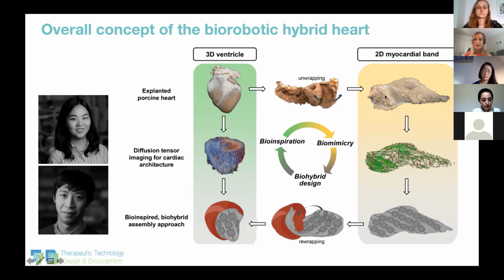And then we collaborated with Professor Chris Nguyen at MGH, or Mass General Hospital. He's also part of the Martinos Imaging Center, and he does advanced cardiac magnetic resonance imaging. In particular, we use diffusion tensor imaging, which you see here. You can basically use a technique called tractography to outline the orientation of the muscle fibers in the band. So now we have this 2D band and we scan it, and we're able to identify the orientation of the muscle fibers in the band.